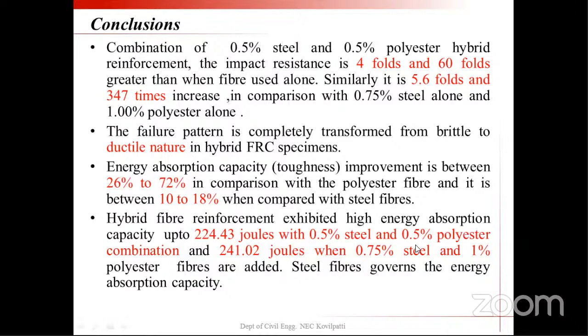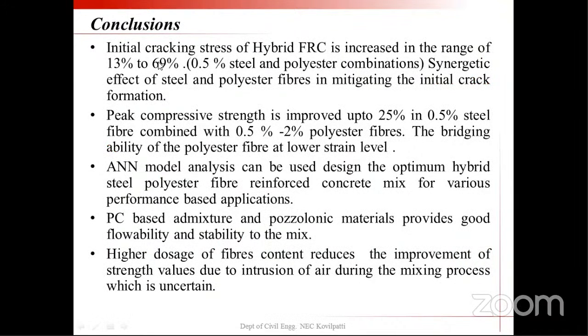In hybrid fiber reinforced concrete, the highest energy absorption is exhibited, 224 joules with 0.5 steel and 0.5 polyester in combination, and 241 joules with 0.75 steel and 1% polyester. So from all these results, I understood steel fibers dominated the entire energy absorption capacity. And also initial cracking stress has been improved from 13 to 69%, and peak compressive strength under uniaxial compression, while measuring the toughening, is also improved up to 25%.